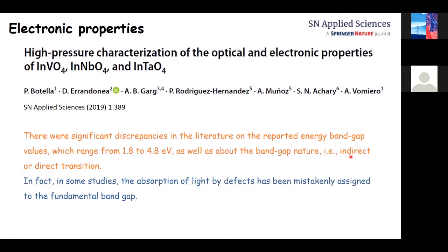Okay, so now let me focus the remainder of this talk on the electronic properties, which was the main topic of the article we published some time ago in SN Applied Sciences, and which has gotten a lot of attention and a lot of citations. Here we focus on the band gap. The main reason for focusing on the band gap was that, as I mentioned at the beginning, there were significant discrepancies in the literature on the energy of the band gap. For instance, in indium vanadate, there were results going from 1.8 to 4.8 eV, which is nearly 3 times the lowest value. And there was a debate about whether the transition was indirect or direct.